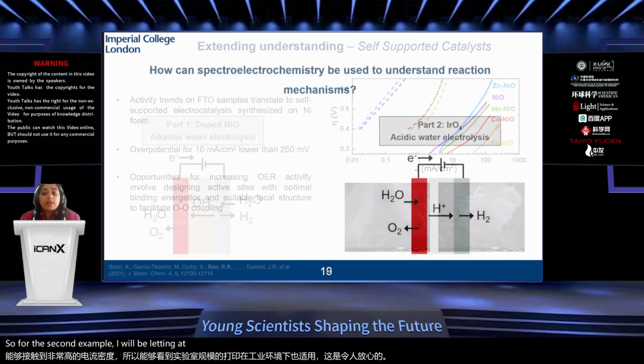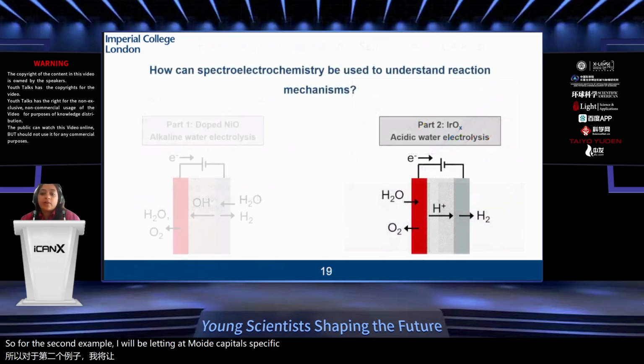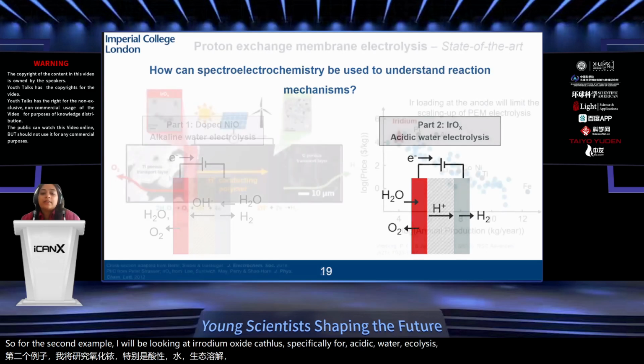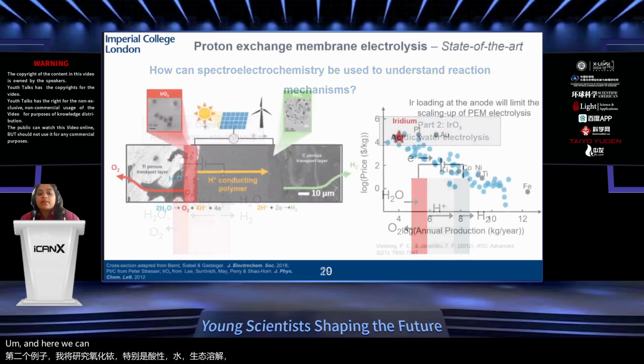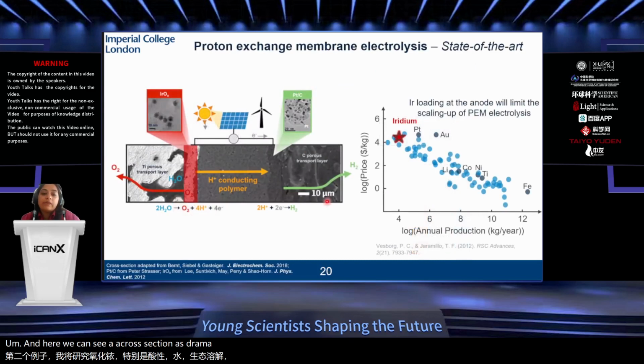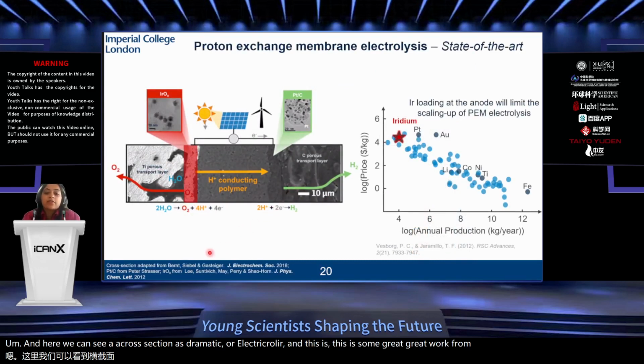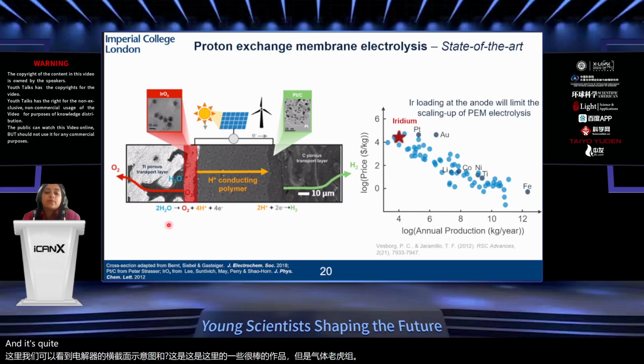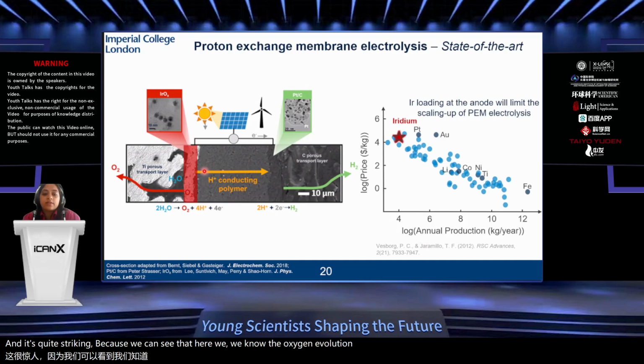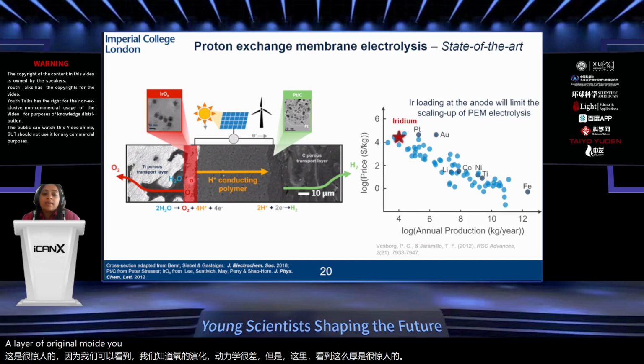For the second example, I will be looking at iridium oxide catalysts, specifically for acidic water electrolysis. Here we can see a cross-sectional schematic of an electrolyzer, and this is some great work from Hubert Gasteiger's group. It's quite striking because we know the oxygen evolution has really poor kinetics, and it's striking to see how thick a layer of iridium oxide you need in acidic electrolyte to be able to drive this reaction.